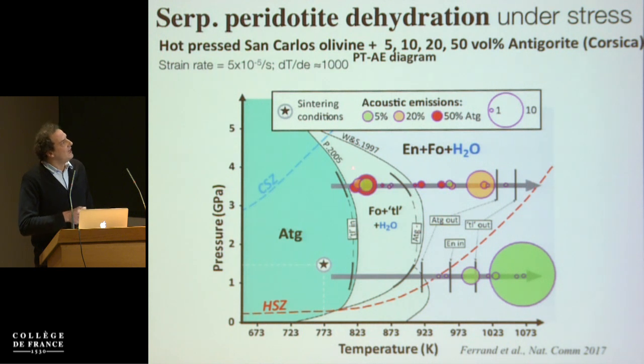And you see that at high pressure, we do see acoustic emission being triggered immediately when we have the dehydration, whereas at low pressure, we seem to have acoustic emission being triggered only at very high temperature, when we complete the dehydration. This is a technical issue, but it is linked to the fact that the Clapeyron slope of the reaction, which is the limit here, has a negative slope. So the delta V is negative, and a negative delta V seems more likely to trigger acoustic emission.